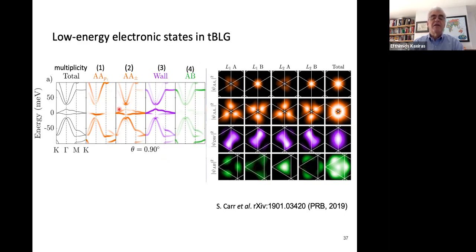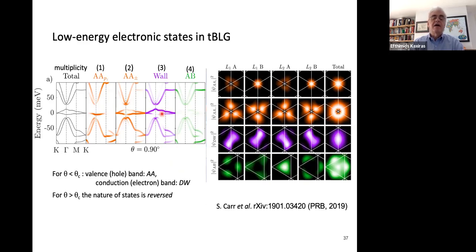And you see that the flat bands in the middle here near the Fermi level contain behavior of electrons near the AA regions as well as on the walls. And in fact, the 2 bands change character as you go through the critical value, the magic angle. So the valence band, the hole band, which is below the Fermi level, has AA character, is mostly concentrated in these orange regions. And the conduction band, the unoccupied states, have domain wall character if the twist angle is a little below the critical value. If you make the twist angle a little bit above the critical value, the nature of these states changes. So they're really very closely interrelated states.